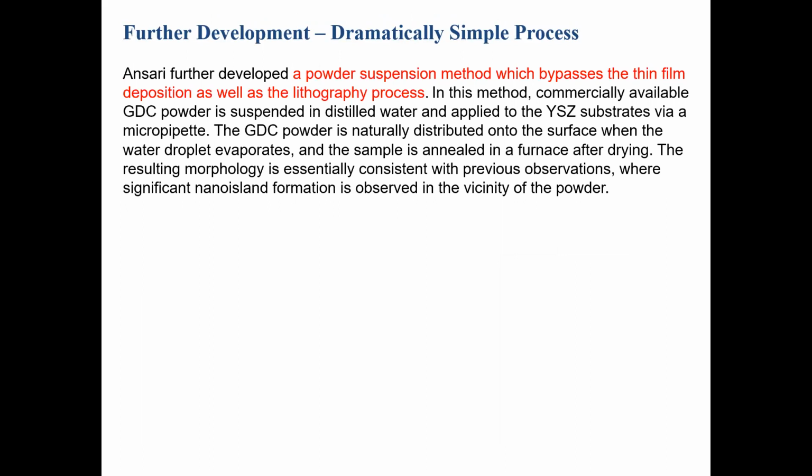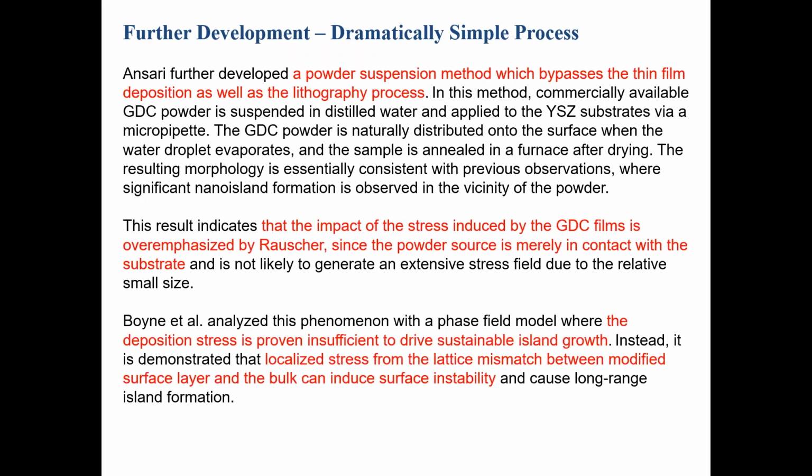What it does is it takes powders of various oxides, creates a water suspension, puts a few droplets of that suspended particles on the substrate, and then dries it out and heat treats it. And then he found out actually that you don't need all this sort of stress created during the deposition.